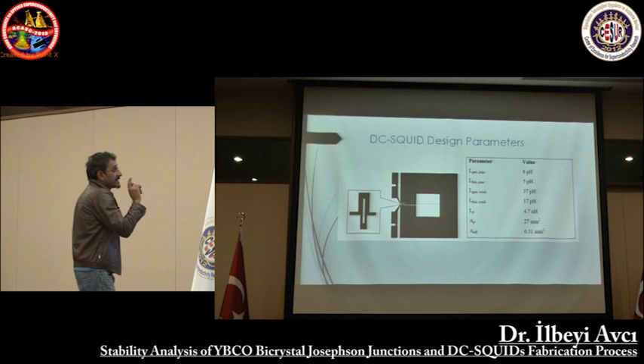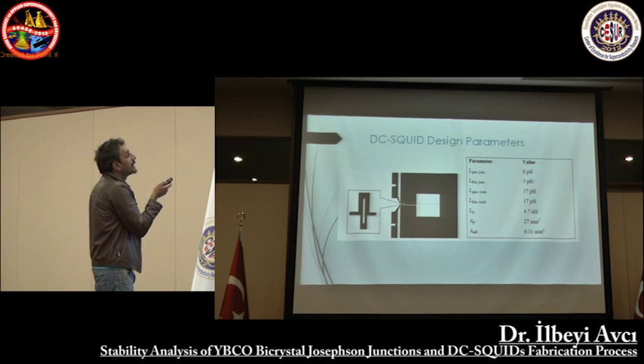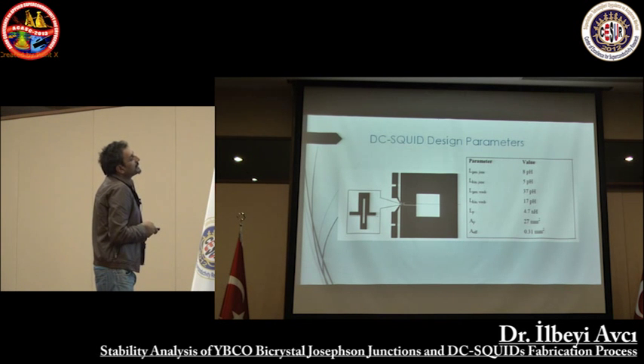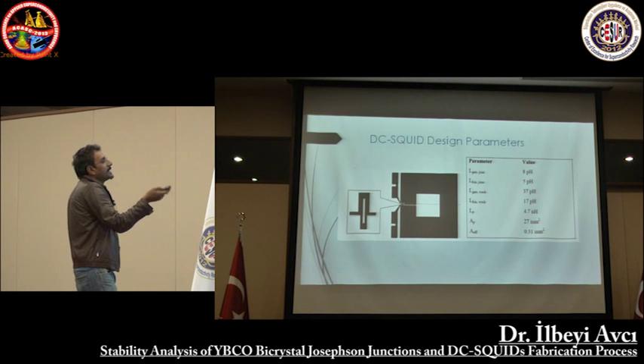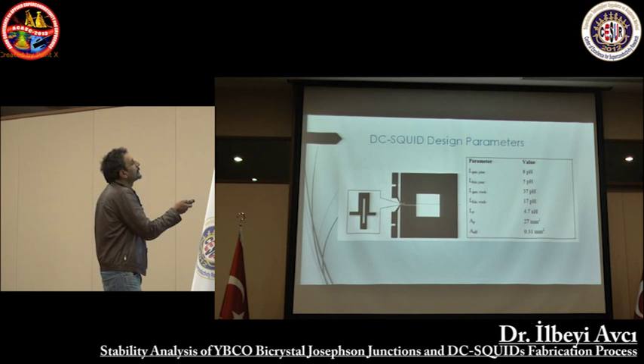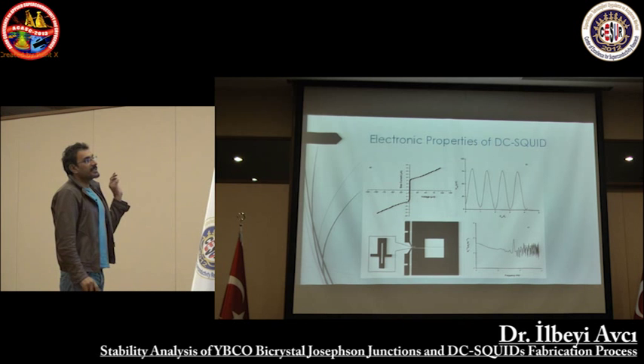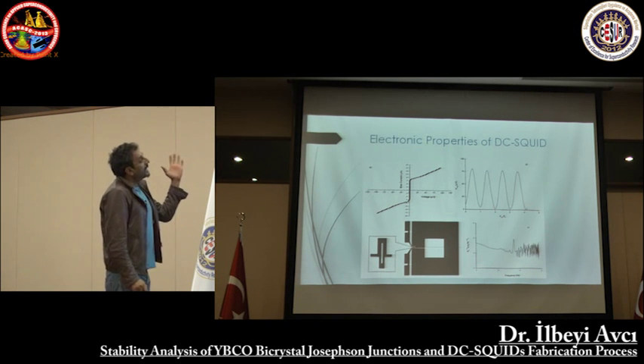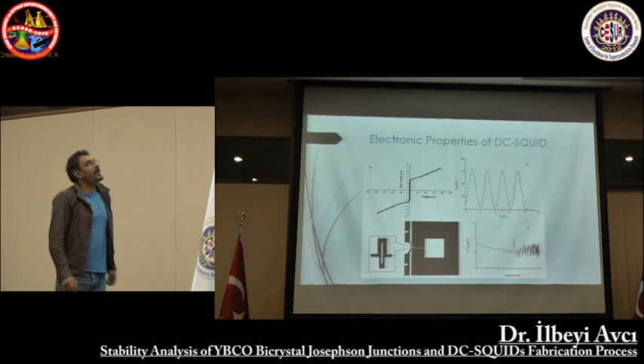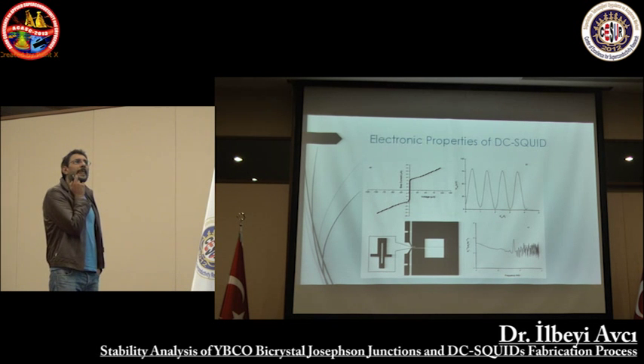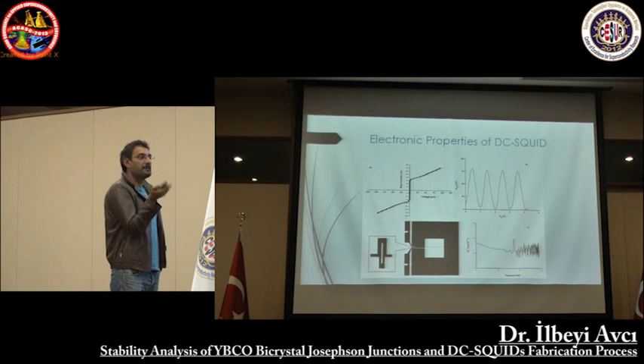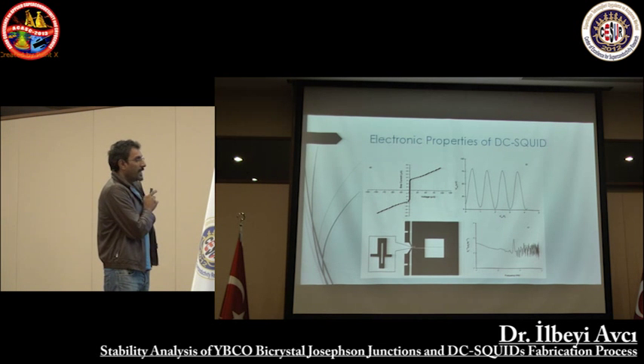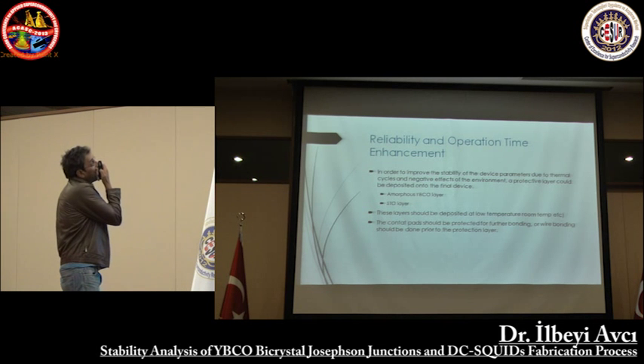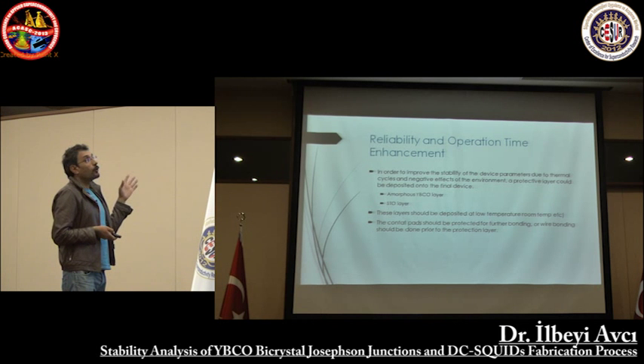This is our single SQUID, including the optimized Josephson junctions, and these are our design parameters. Before fabricating the SQUID, you have to get the design parameters in order to get the layout: geometric inductance, kinetic inductance, pickup loop area, effective area, and so forth. This is the best SQUID that we have ever gotten. In the literature, maybe you can find levels of about 100 or something like 300 microvolts, single SQUID Vpp. Here we got 100 microvolts, and this is one of the best results in the literature for YBCO bicrystal junctions.